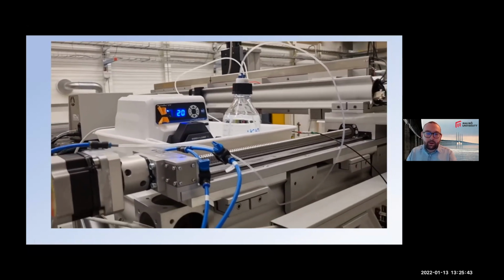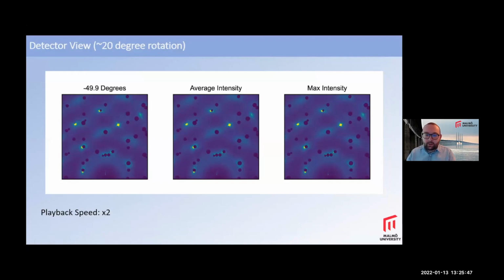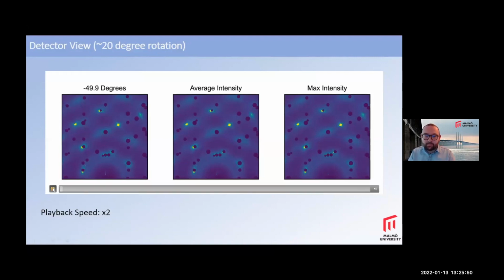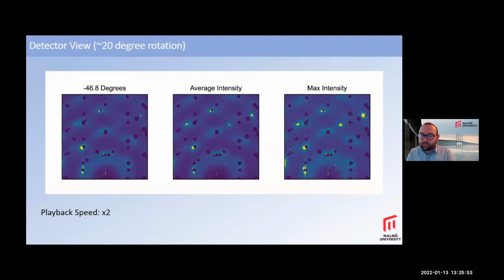Okay. So what does it look like on your detector? As you rotate your sample, the Ewald sphere starts to intercept the crystal truncation rods, and you see intensity moving up your detector. You can process this in two simple ways. You can average the intensity, or you can take the maximum intensity across the rotation. What you can see is if you take a big rotation, the average intensity quickly becomes saturated by the background. So often I'll present images with the maximum intensity, but you can get the summed or average intensity just by choosing a smaller angular range.